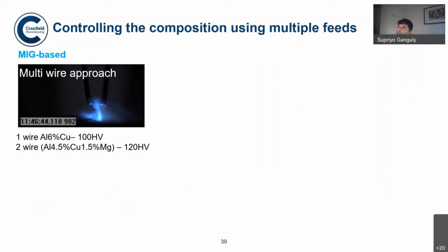So, controlling composition with a multi-wire approach. This work was also done by one of our students a while back. It was basically the root, the first seed project, we can say, from which we had this concept. So he added multiple wires in order to avoid solidification cracking, because in some of the aluminum alloys, solidification cracking becomes inevitable because of the solidification path and the phases that form during the solidification process.